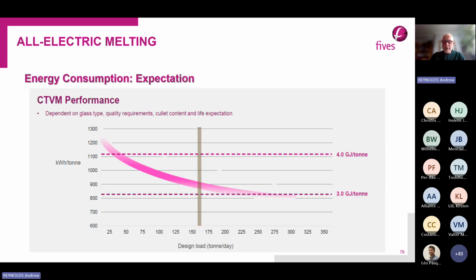One of the other important points with the project is that because electric furnaces are already very energy efficient, we're on the part of the curve of specific consumption versus design load where the curve has already become quite flat. So in fact, a 160 ton per day furnace is predicted to run at about 900 kilowatt hours per ton of glass. That's about 3.2 gigajoules per ton. If you size the furnace even bigger, you don't get huge benefit in terms of size. One of the big drivers for gas-fired furnaces has always been that bigger furnaces are better because they're more energy efficient. That becomes less true for electric melting.